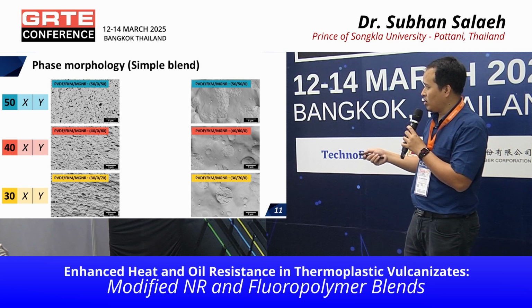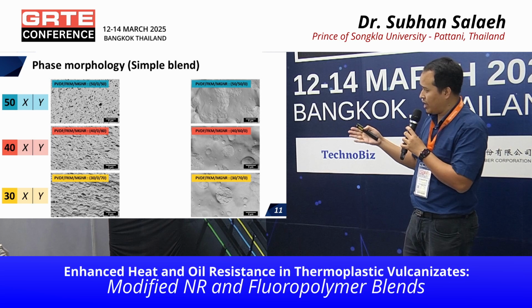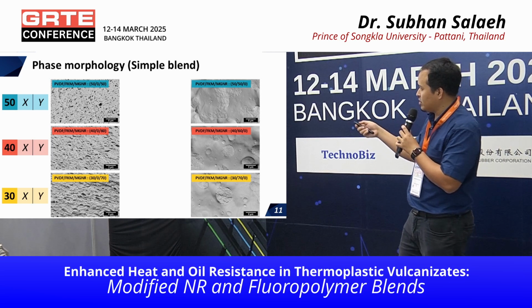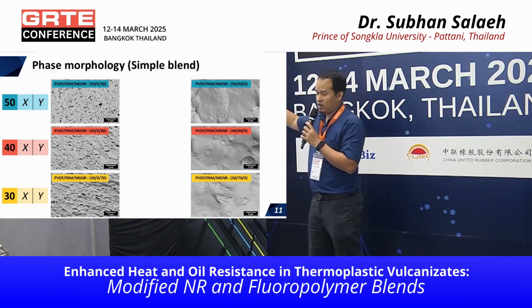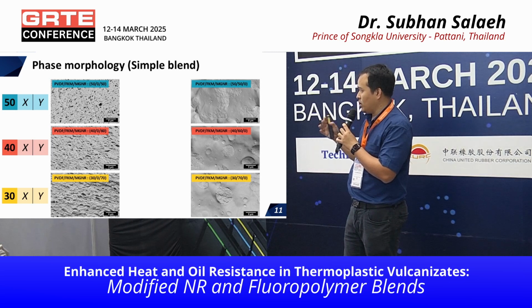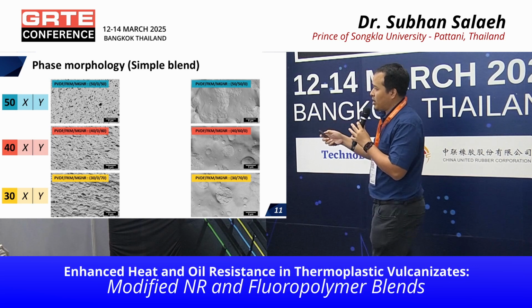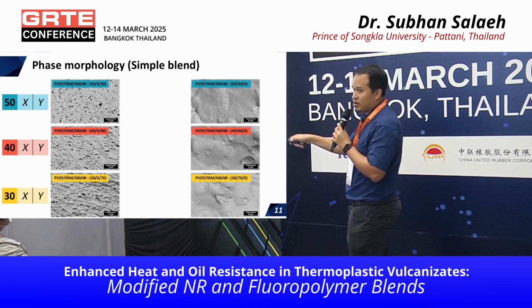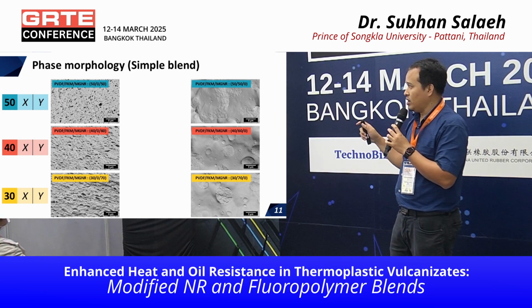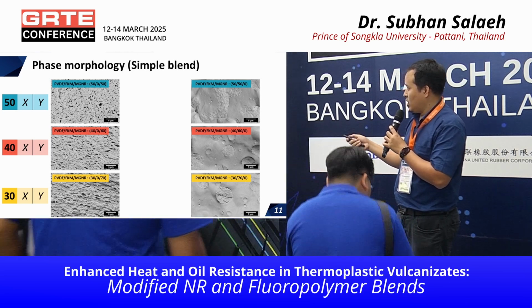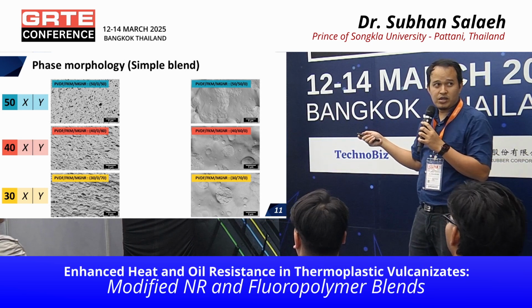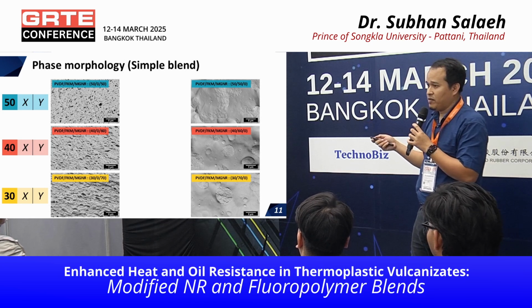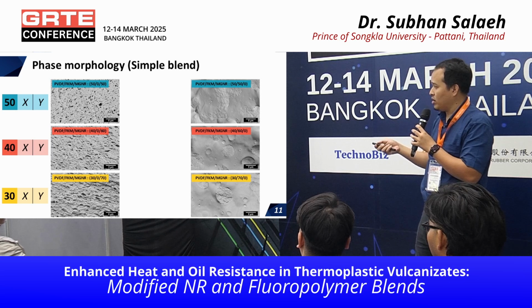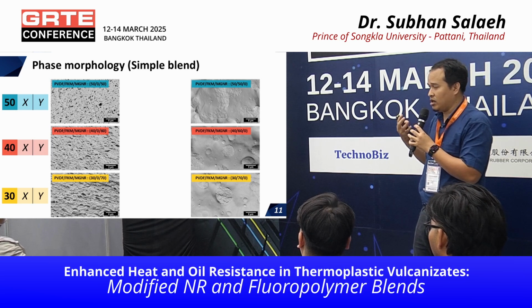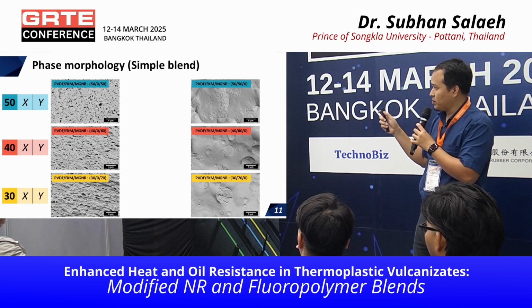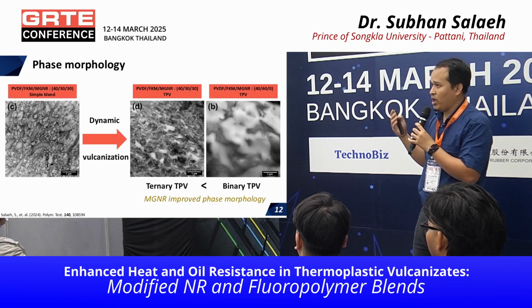And also on the left hand side is only PVDF and MGNR, and the right hand side is only PVDF and FKM. We can see the large PVDF domain for the binary blend of PVDF and FKM due to the different viscosity. But in the case of PVDF and MGNR, we can see the good dispersion of MGNR in the PVDF due to the interaction. And also for the ternary blend, we can see the fine dispersion of FKM, MGNR, and PVDF. This is the combination of the three components in the TPV. The hole is from the extraction of the MGNR with toluene. So we can see that the ternary blend shows good morphology as compared with the binary blend.